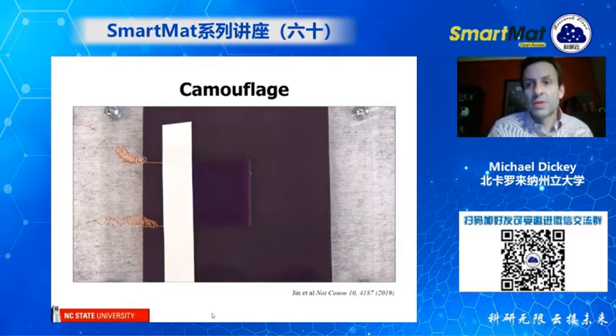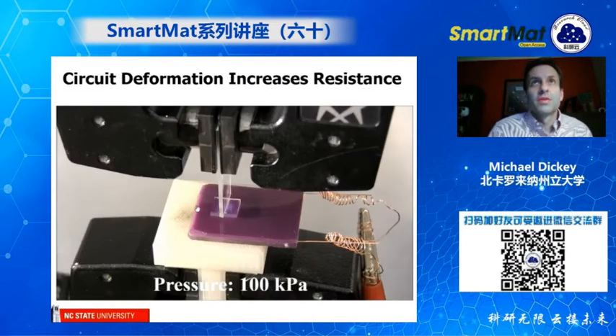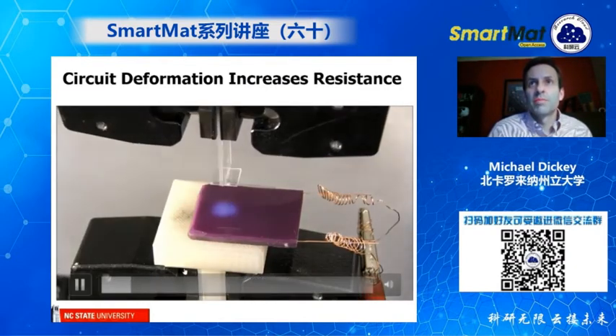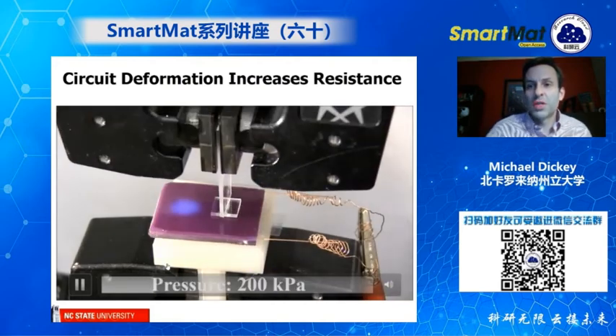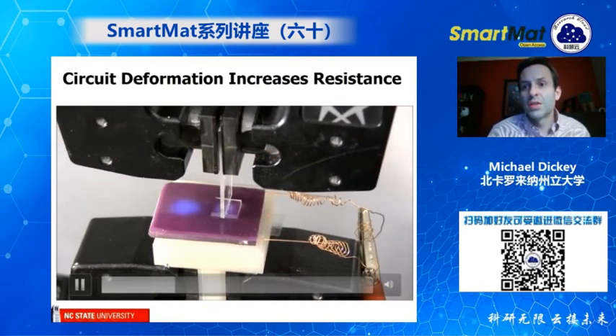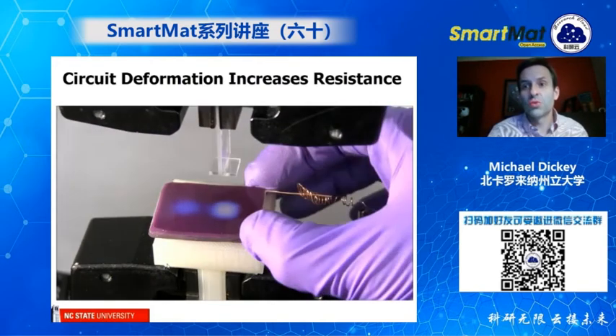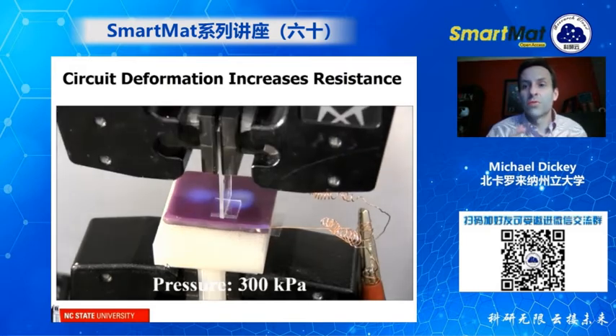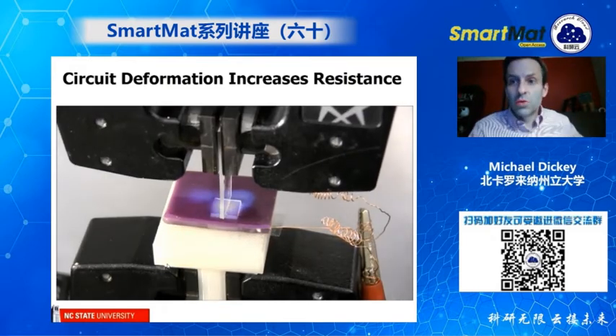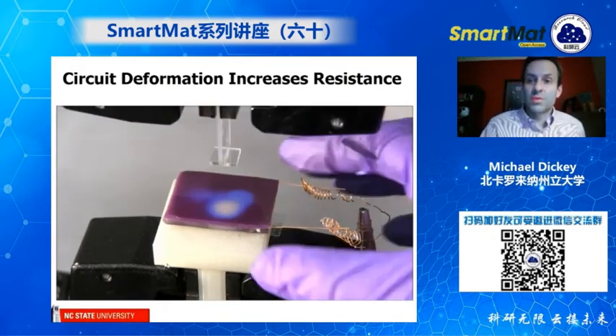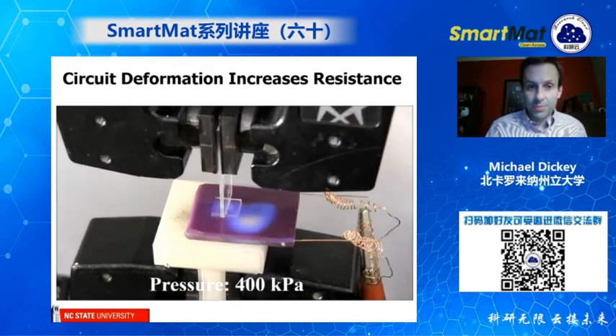Where this gets interesting from a scientific standpoint is because we're using liquid metal, we can actually deform the circuit. So if you take basically this piece of plastic and you push down on this circuit, you change the dimensions and you change the joule heating. So when you deform the circuit, you make the local resistance higher and you cause it to change color.